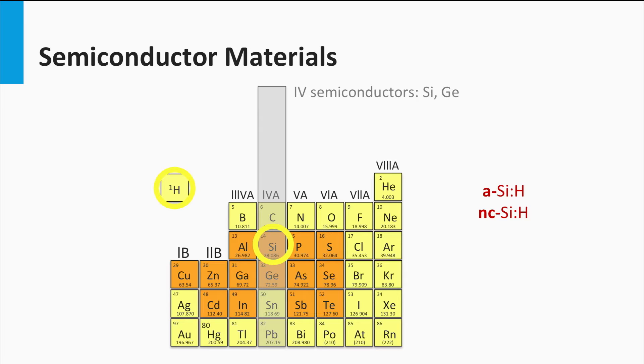Focusing on the composition of the various alloys: we have hydrogenated amorphous silicon and nanocrystalline silicon. This means that we have a lattice of silicon in which some of the valence electrons are passivated by hydrogen. The ':H' in the abbreviation corresponds to the incorporated hydrogen. The hydrogen content for these types of silicon alloys typically ranges from 5 up to 15%.